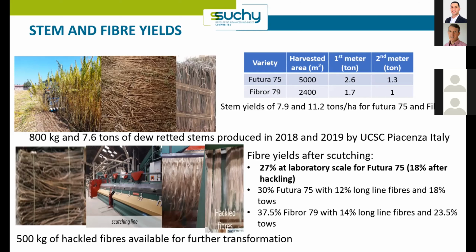So high biomass was obtained. Biomass is good, but what is really our interest are fibers. And for fibers, fibers were extracted using scutching and hackling. So tests were performed at the lab scale with different settings. A lot of settings were tried. And we managed to obtain very high yields at the laboratory scale: 27% of the stem mass transformed into fibers, and 18% after hackling.